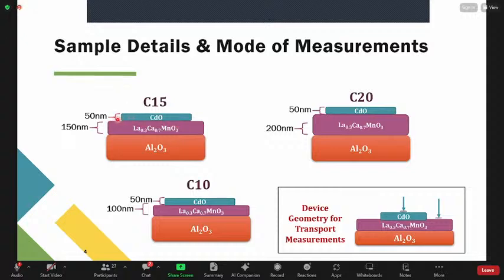The thickness is given here. CDO is kept fixed at 50 nanometer, and for the LCMO layer we are changing the thickness: 100 nanometer, 150 nanometer, and 200 nanometer. According to that, the sample codes are given. So 100 nanometer LCMO means C10, 150 means C15, and for 200 nanometer it is C20.